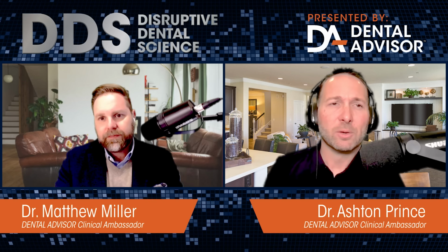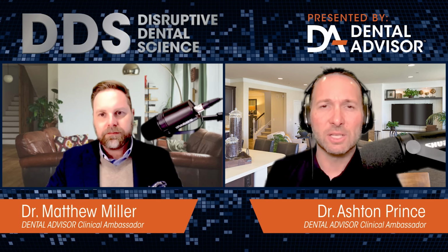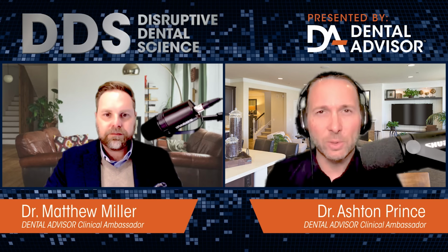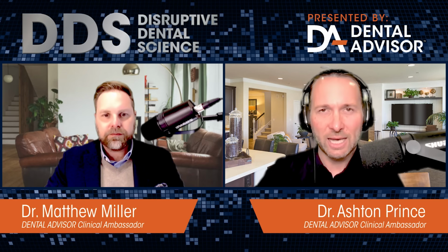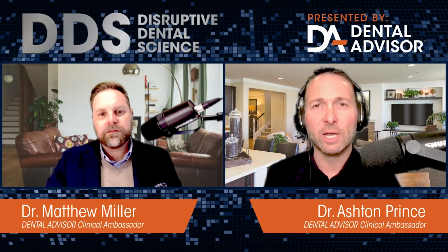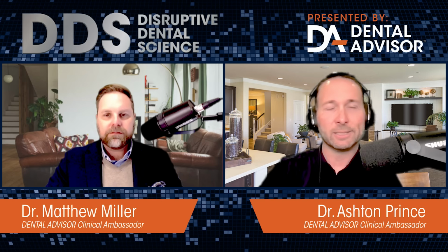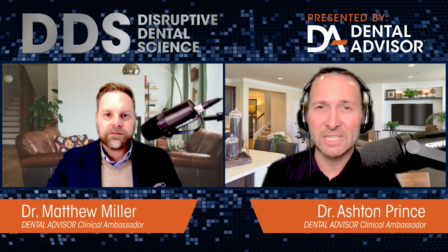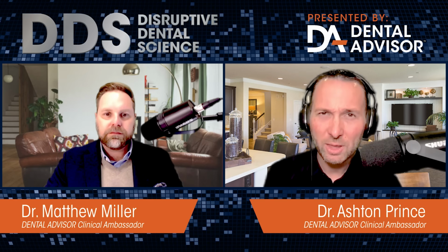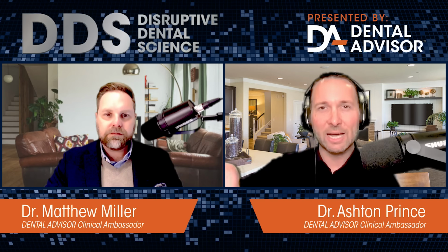It does, and you're exactly right, Matthew. When you start talking about what the acronym AEP actually stands for, the E is enhancing. It's an enhancement process that actually goes on here. So you would apply that AEP primer down onto the tooth, and as soon as the G-CEM ONE interacts with that material, it starts to almost instantaneously set up a lot faster in its self-curing mode than it would if you were trying to hit it with a light. So it does cure towards the tooth, which is something I love that it does, as opposed to pulling away from it. For me personally, I swear that most bonding agents will start to dehydrate a tooth. This will actually go towards it. It's something that I've had to be a little cautious with, because if I do have the AEP on it, I really feel like if I'm going to be putting this restoration on, I don't have a lot of working time to be messing around with it.